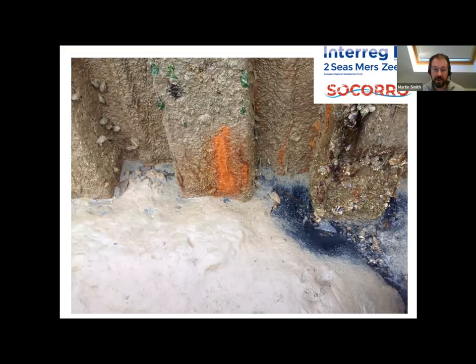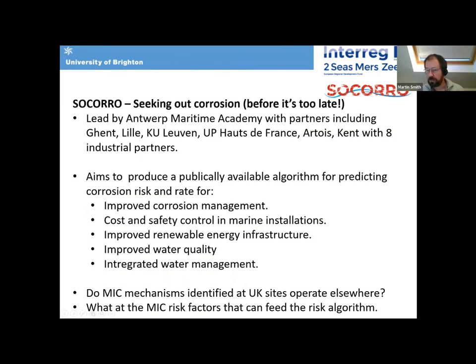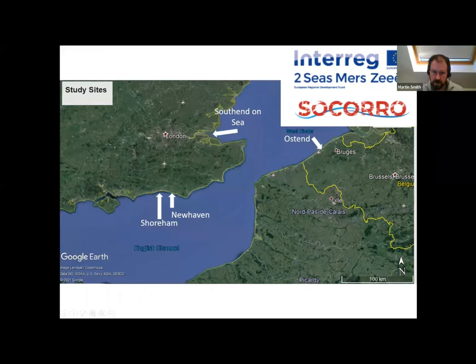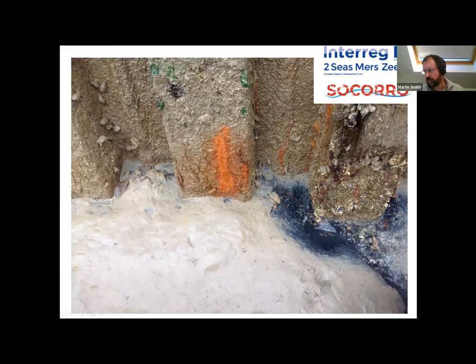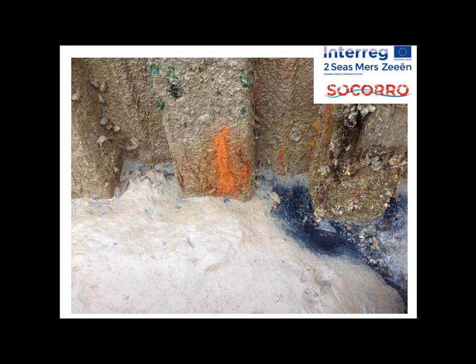So we get to do some really exotic fieldwork. This is Shoreham Harbour at low tide. We've got typical estuarine muds here, and you can see immediately below the surface, they're very, very dark in colour. So this is one of the key factors we've got to identify first. We've got extensive evidence where we have microbially influenced corrosion problems that we've got sulfate-reducing bacteria in the environment anyway. And what we were initially concerned about are these features, these orange blisters.